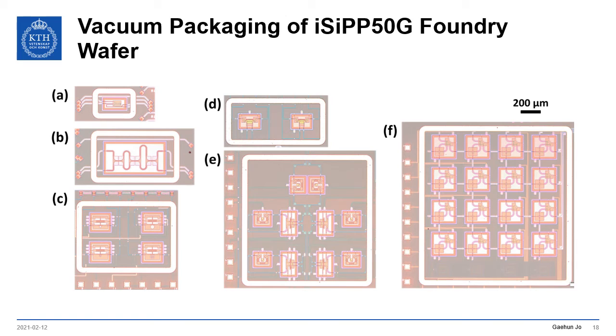To demonstrate the feasibility of the proposed wafer-level vacuum packaging, an SOI sealing cap wafer contains 30 micrometer thick caps with different dimensions, roughly from 300 micrometers up to 3 by 3 millimeters. These figures show examples of different photonic devices using different shapes and dimensions of the sealing caps.